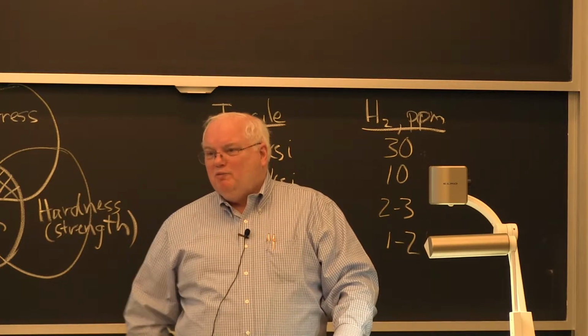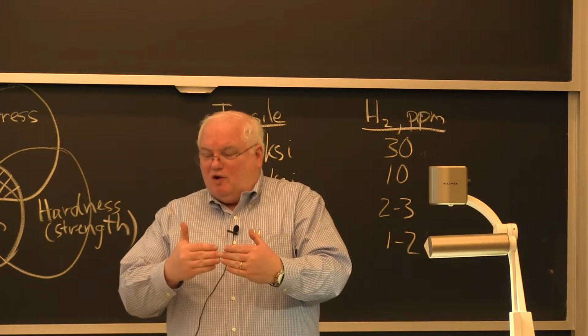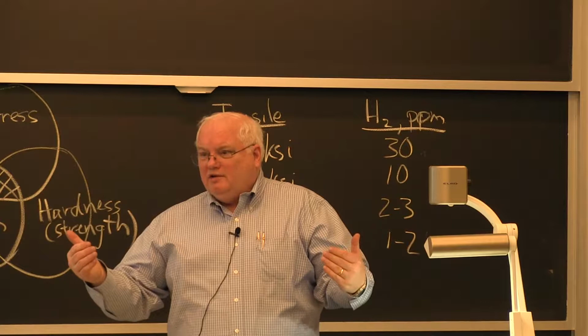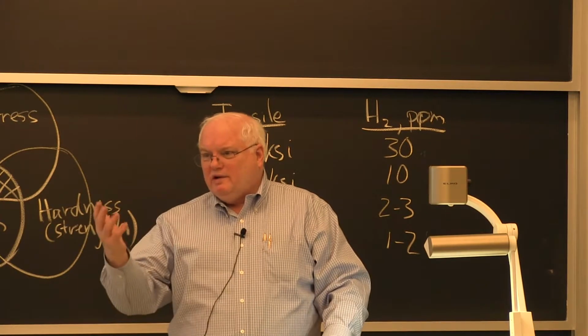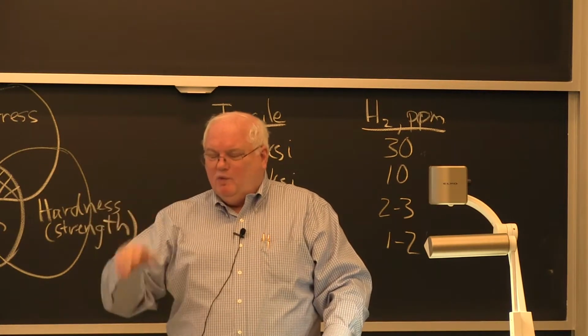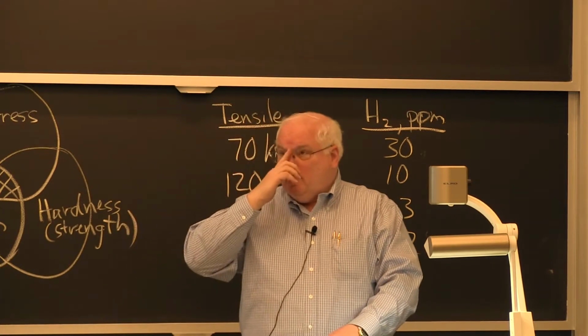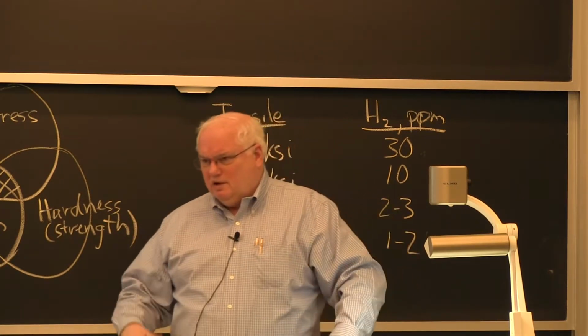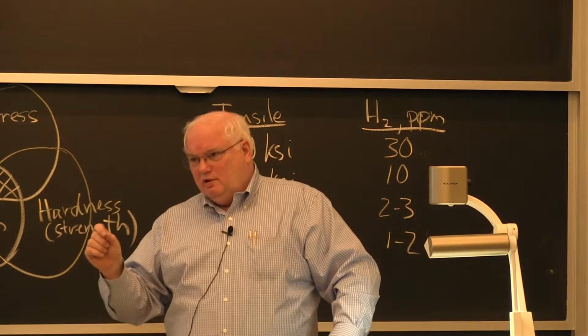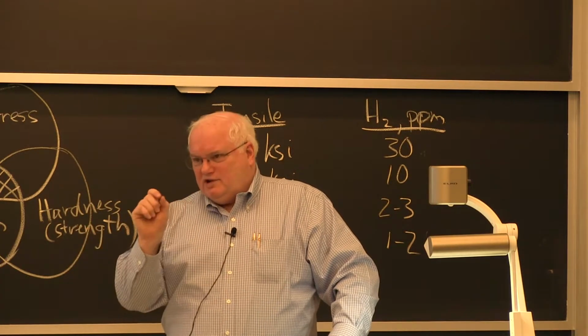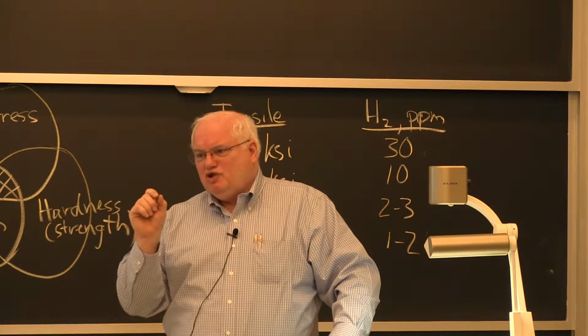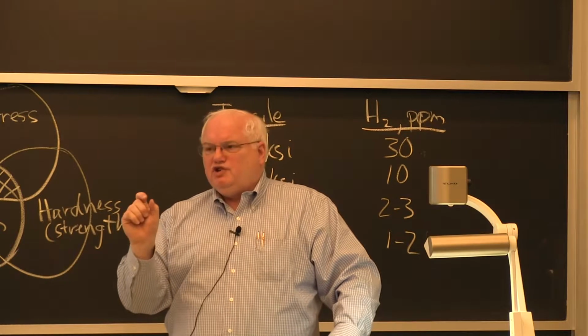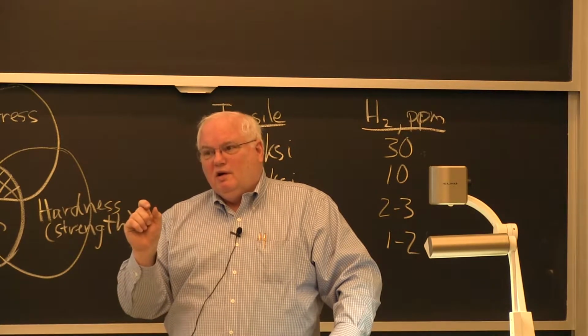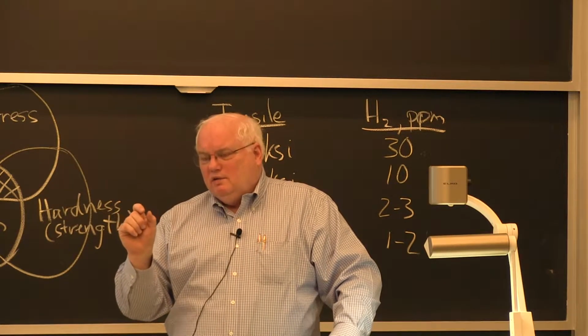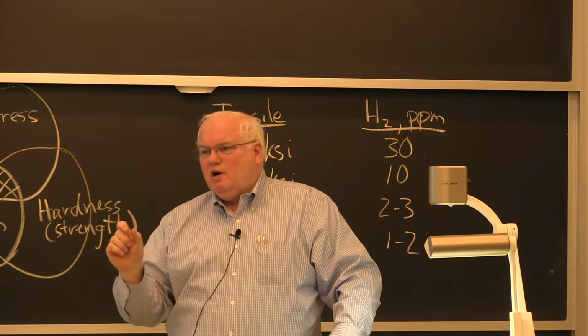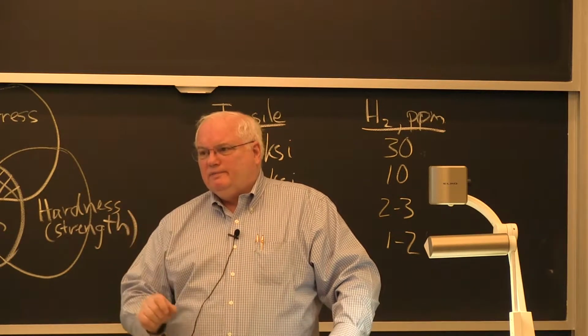But you start thinking about a quarter of an inch over 100 yards, you can calculate what parts per thousand is, and it's going to be, I don't remember, 1 in 20,000. It's more than 1 in 20,000. It's 1 in 30,000 or 1 in 100,000. If you start getting down to nanometers of a silicon chip, those dimensions, over the length of the chip, which is about a centimeter, you're also getting into the one part in tens of thousands or hundreds of thousands.